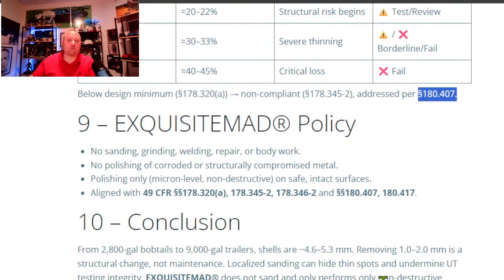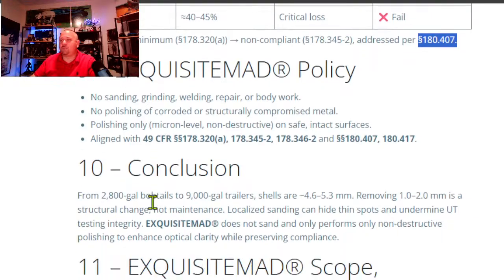Below design minimum is dictated by regulation 178.320A. Non-compliant is 178.345-2. Addressed in 180.407. These are laws, rules, and regulations that are set by the federal government. Our policy is no sanding, grinding, welding, repair, or bodywork. We do not polish, no polishing of corroded or structurally compromised metal. Polishing only micron level, non-destructive on safe, intact surfaces.